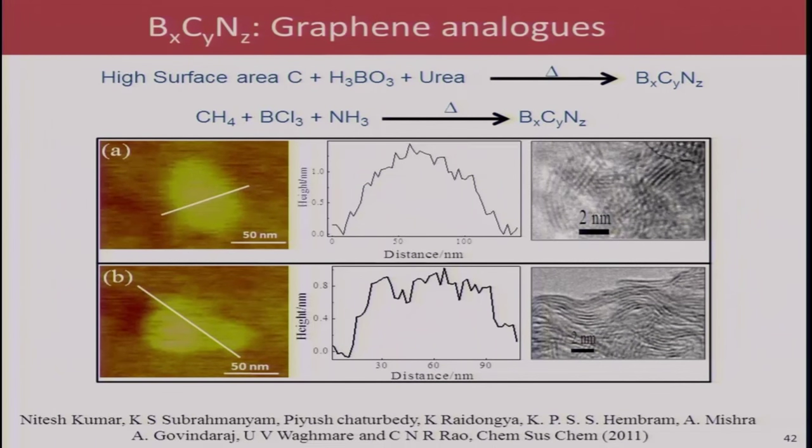Okay. Well, we have made borocarbon nitrides by a number of methods. They have all kinds of layer structures. You can make single-layer materials, two-layer materials, all kinds of materials. In the last two months, I found the best way to do it is to take single-layer graphene or two-layer graphene and react it, and then you get a pure, large layer of borocarbon nitride. In the same sheet, you have domains of boron nitride, borocarbon nitride, and carbon. You can vary the proportions of that, so you'll have unusual electrical properties. We have made transistors out of it as of last month.